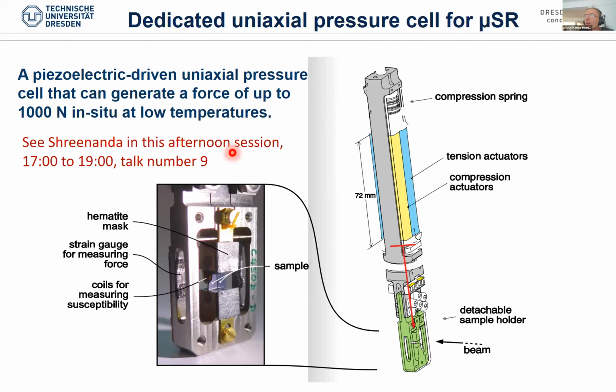We need a much larger sample to get muons onto our sample here. So the beam size is approximately 7 to 8 millimeters. So we need to strongly increase the area and also the thickness of the sample, which means we need to have an in situ uniaxial pressure device, which can give forces up to 100 kilogram or 1000 newtons. And this took really about 5 years to get to the state where we are now.